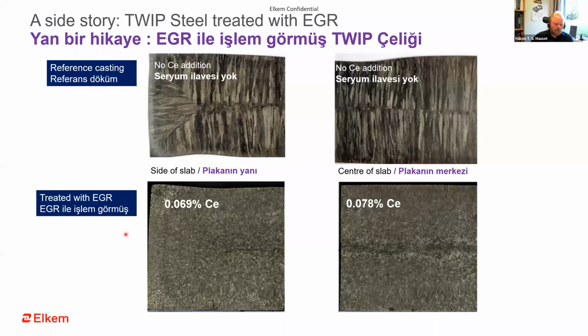But then a trial was done with EGR. You can see that we have around 700 to 800 ppm of cerium. Here we have the side of the slab. So see, it's much more fine-grained. You don't see these columnar grains at all. And same here at the center of the slab. It is much more fine-grained, which should make it easier to hot roll later on. And hopefully it will be less susceptible to cracking during casting.